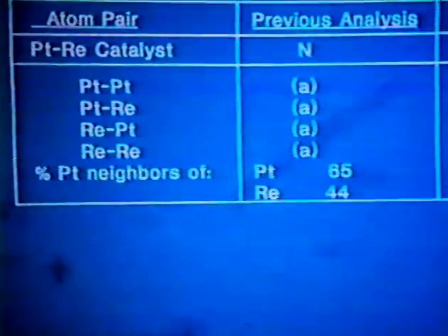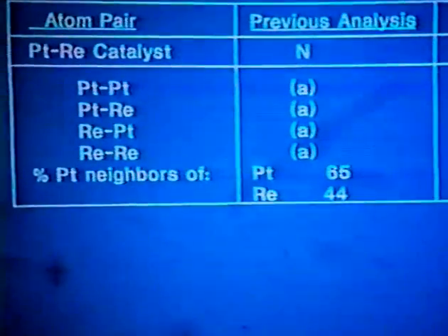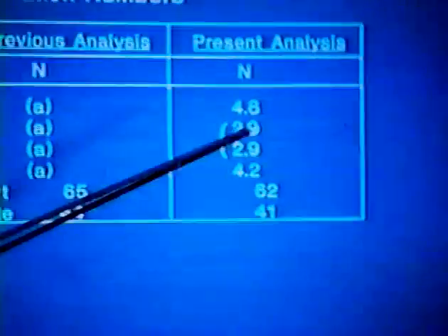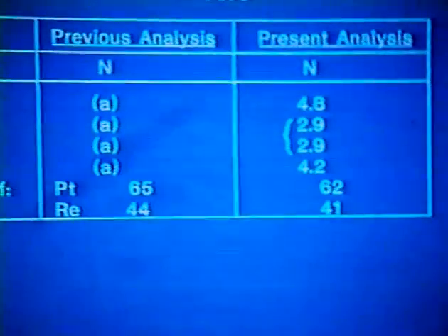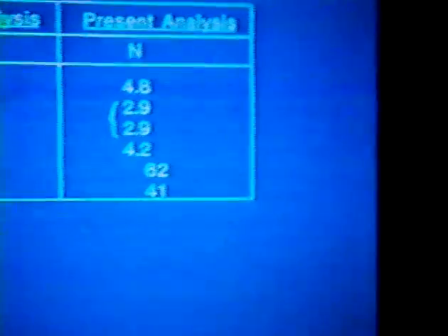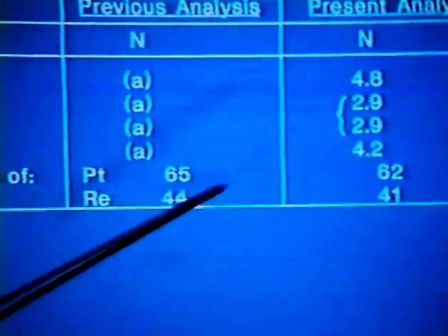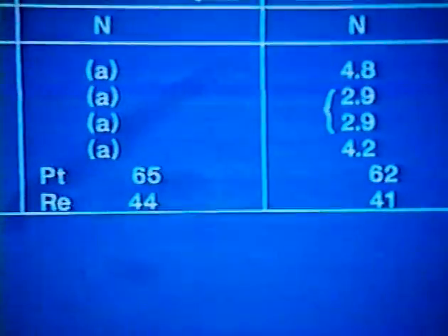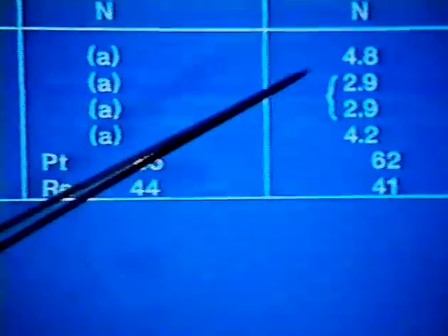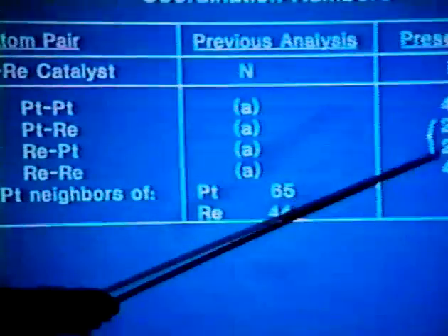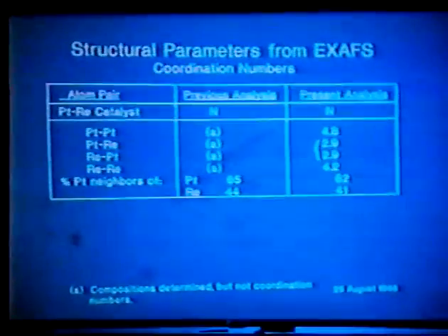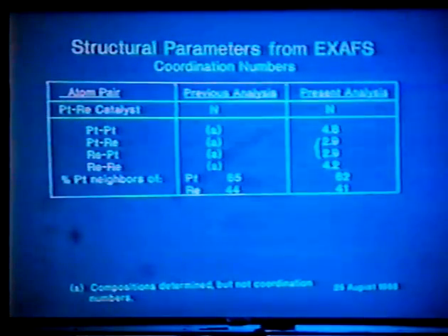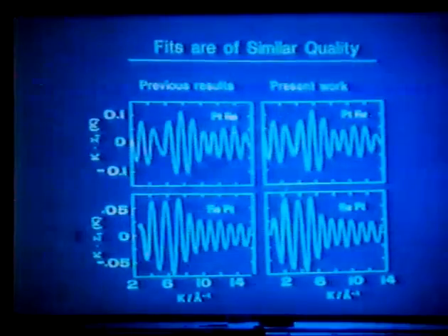Pretty well mixed. In our present analysis, we have fewer adjustable parameters, and consequently the correlations are not as strong. There are not as many variables. And this is what we find, that platinum has 5 platinum neighbors, rhenium-platinum and platinum-rhenium neighbors are about 3, and rhenium has about 4 rhenium neighbors. The compositions of the first coordination shell that you calculate from these are the same as what we determined previously, however. So what we get here is that the total number of metal neighbors about platinum is around 8. Total number of metal neighbors around rhenium is about 7. That would tell you that you've got cluster sizes of 10 to 20 angstroms perhaps, and rhenium is occurring preferentially in the little lower coordinate sites. Next slide.